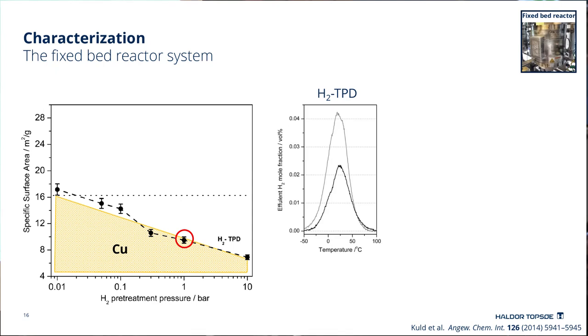So here to the results. Here on the y-axis, we have the specific surface area, or the copper surface area. And here we have, again, the partial pressure of hydrogen during the pretreatment. And what you can see here is the hydrogen TPD data. So initially, we had a nice big hydrogen TPD profile, which is associated with a high area. But if we pretreated the catalyst in pure hydrogen, we saw that this hydrogen TPD decreased quite substantially. So we can see here that the copper area is actually decreasing.